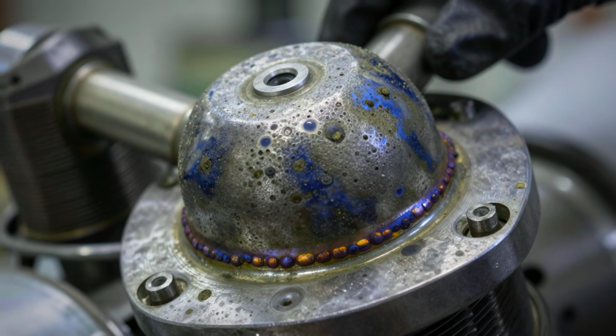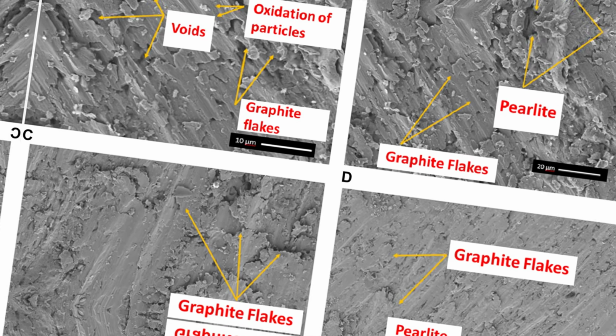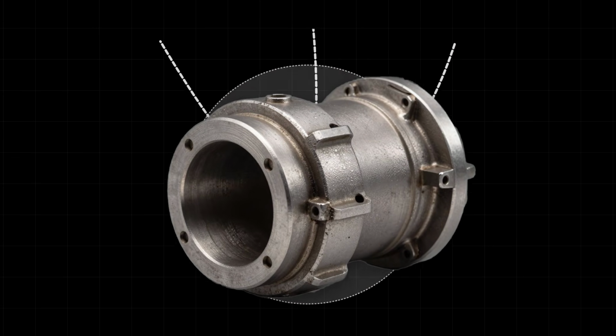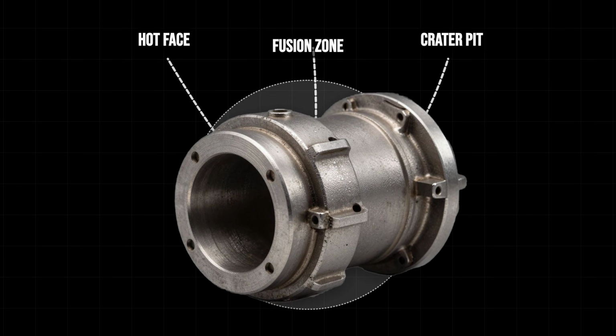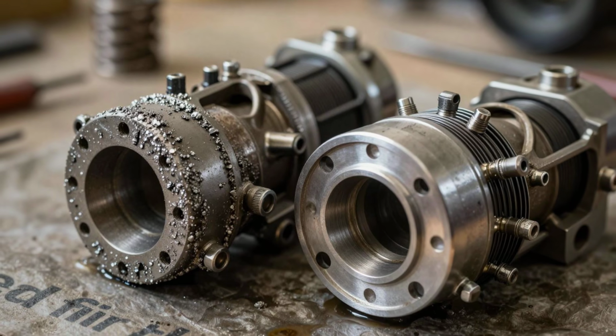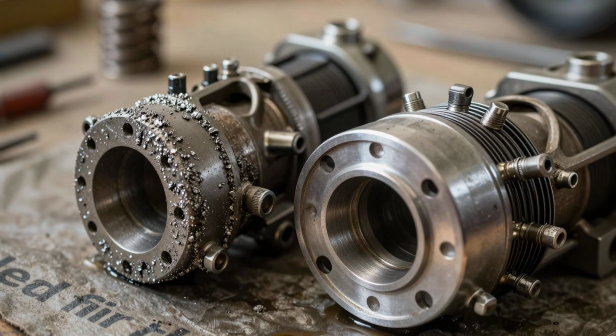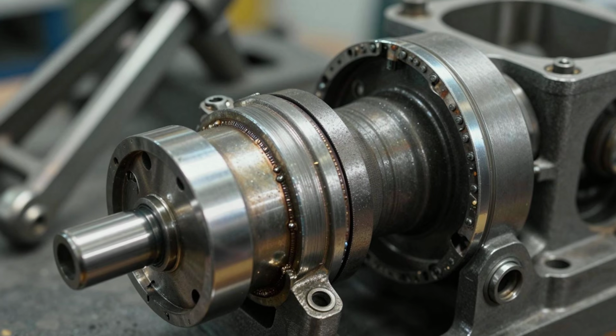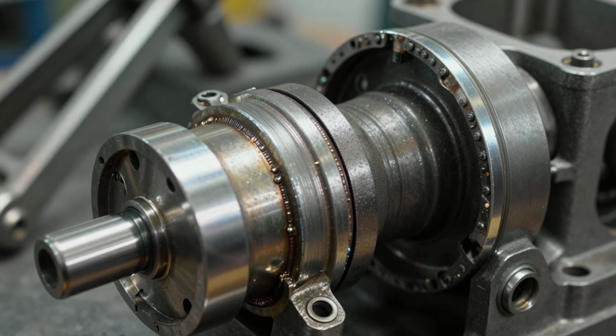This is not slow erosion, it is the mechanical signature of micro-welding in action. Every time the valve slams shut at 800 degrees Celsius, the peaks on the steel fuse to the seat, then shear off, tearing out metal grain by grain. Without the lead film, there is nothing to interrupt this violence. The so-called mechanical paint thinner, G100UL, strips away old deposits, leaving bare metal to face the full brunt of combustion.